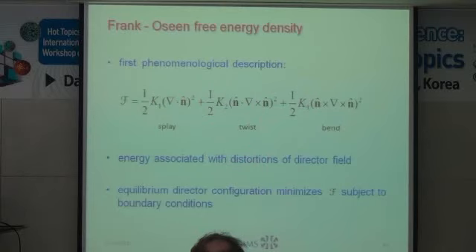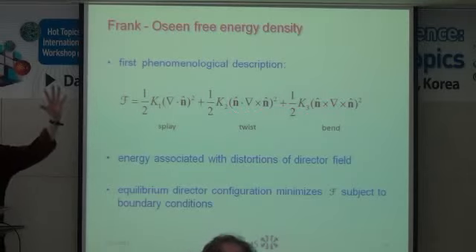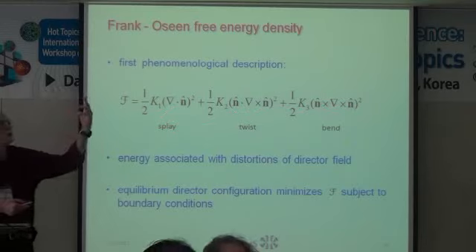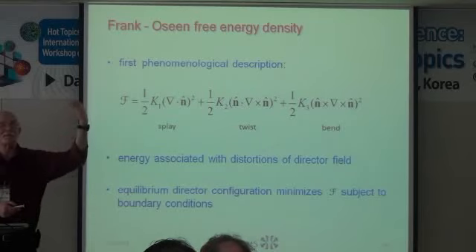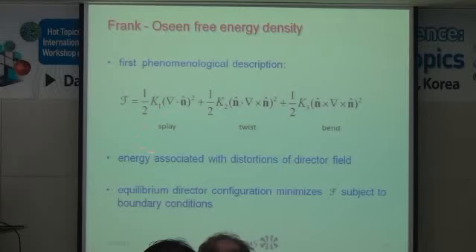And the first free energy that was introduced is by Frank and Oseen, and this is basically just the elastic energy associated with the spatial variations of the director, the direction of average orientation. And these are sort of canonical deformations. The splay corresponds to this. Twist, how can I show twist? Twist corresponds to this, and bend corresponds to this kind of. So these are the three canonical deformations, and these are just elastic constants, and to understand what a liquid crystal will do, one needs to minimize this quantity subject to some boundary conditions that I'll talk about in a minute.